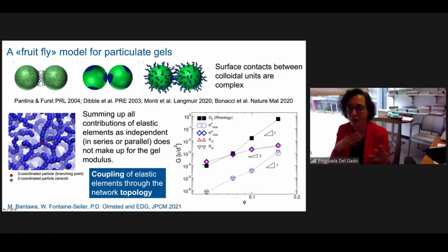And we can combine them, of course, in different ways, in series, in parallel. For example, imagine that they are connected in series or in parallel in our network. Or we can measure the full squares, they are the whole modulus that we measure. And so we can see that at low volume fraction, basically, just adding up these elements as if they were independent, we can basically justify the whole elastic modulus with the specific combination of these elements. But if we go to higher volume fraction, then there is clearly a significant part of the modulus that is actually not captured by just this combination of these elements as if they were independent.